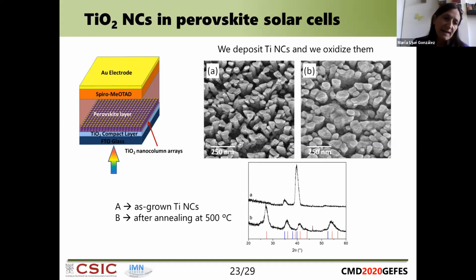We cannot directly deposit titanium dioxide nanocolumns in our system because we only have metals, so what we did was to deposit titanium nanocolumns, and I wanted to show this image because I think these nanocolumns are so beautiful. Then we did an annealing at 500 degrees and were able to oxidize the nanocolumns. We monitored the oxidation by looking at the X-ray diffraction peaks, and we saw how the metallic titanium peak disappeared and the peaks corresponding to the oxide phases appeared.